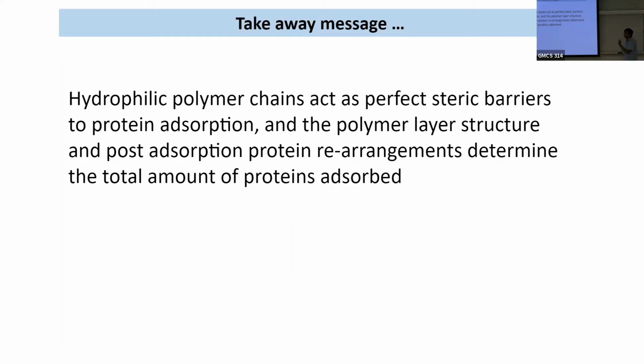There was a mistaken assumption that we made because we had to find that upper bound to calculate the probabilities, and we found that upper bound using this approximation where you said all the open available area is available for the protein to sit. And that's not entirely true. But then we figured out that luckily it worked out for us because of how these surfaces are formed, you automatically have this packing of either polymers or proteins together.